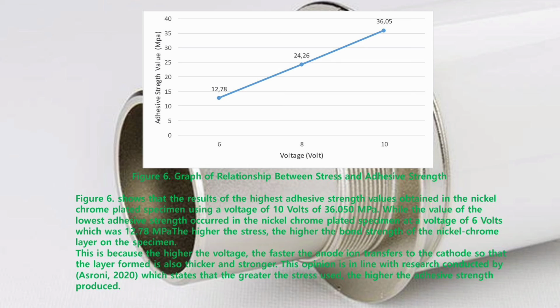The higher the stress, the higher the bond strength of the nickel chrome layer on the specimen. This is because the higher the voltage, the faster the anode ion transfer to the cathode, so that the layer formed is also thicker and stronger. This opinion is in line with research conducted by Asroni 2020, which states that the greater the stress used, the higher the adhesive strength produced.